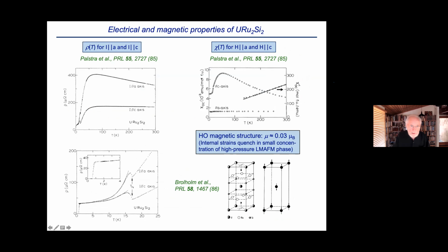And here's some of the really nice data on the single crystals from Palstra and co-workers. There's a resistivity versus temperature. This is along the c-axis and in the basal plane. And then you see for this curve, you get an increase of resistivity, Kondo-like scattering, rolls over and approaches a coherent ground state. And then at a certain point, you see the formation of this hidden order phase in these features here, which are shown in the lower part of the figure in more detail. And then you see the drop in resistivity due to the superconductivity. Here you see the magnetic susceptibility along the easy axis and the hard axis. And at high temperatures, you get Curie-Weiss behavior with the effective moment close to the free ion value. Then it rolls over, and again, you see a little kink due to the hidden order.